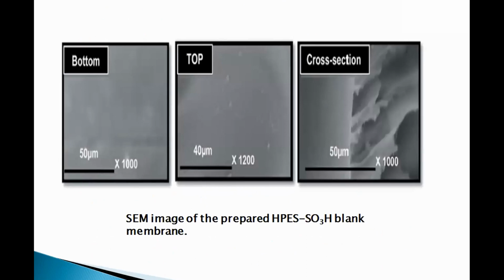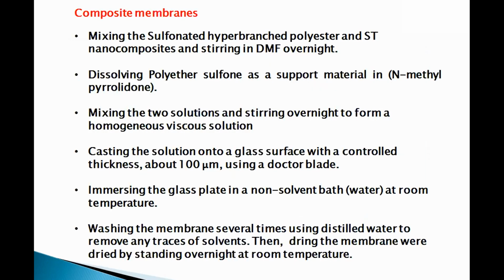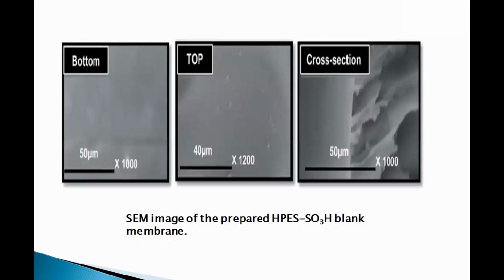These are the analysis images for the prepared hyperbranched ether sulfone with sulfonic group, the blank membrane. As we can see, there are no pores and the surface is smooth. The composite membrane is prepared by the same method as before, but the only different step is adding the sodium titanate to the composite. And these are also the images of the composite membrane.